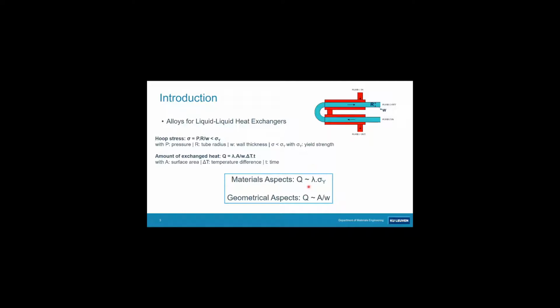So this talk will mainly focus on the material aspects, and I will just show a few slides on the geometry design aspects. So a small recap for most of us, this is from the same course. So basically showing the different effects of strengthening mechanisms, starting from pure copper with a fairly low yield strength, but a very high electrical conductivity, and how the different strengthening mechanisms influence both these material properties. So you notice if you form solid solutions, you can strengthen the material, but you significantly compromise on its conductivity. On the other hand, introducing more dislocations and dislocation structures will work harden the material. It will get stronger with minor influence on the conductivity, and then a kind of compromise between both of them in terms of strengthening effect. Probably the strongest are precipitation strengthened systems with an average effect on the conductivity.